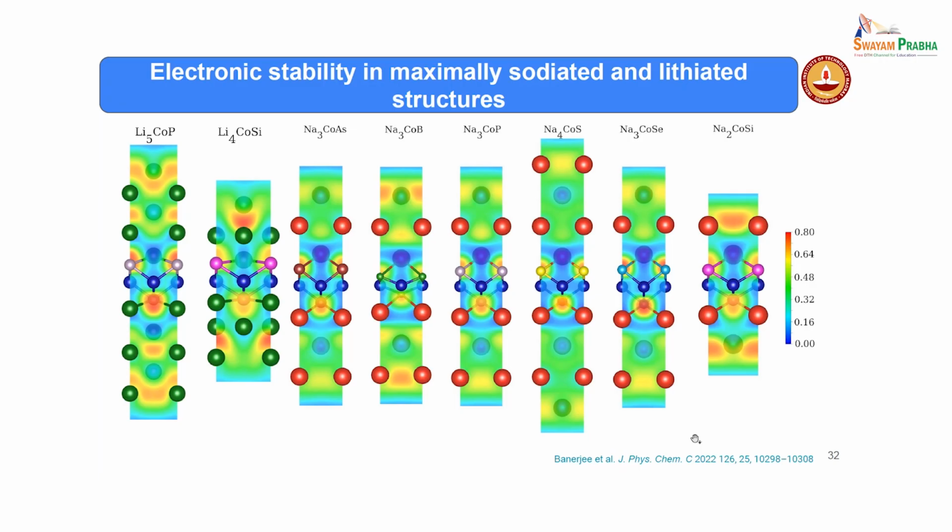That is okay. So if you are considering these, you can clearly see that at the beginning, in the first layer, there is only ionic type interaction, but afterwards there are free electron gas type interactions between the atoms, that is helping to load a larger number of atoms in the cases of lithium and sodium.